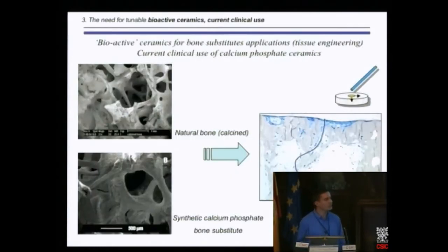So what is the current clinical use? We already use calcium phosphate ceramics. So here is a natural bone, especially the mineral part of this natural bone, and here is a synthetic calcium phosphate bone substitute we have made, for example, in the lab. So the idea is to mimic the structure of the bone at the micro level. This is 1 millimeter in size, 500 microns in size, so about the same type of structure. So the first idea is to mimic the structure. And especially what we want is to have a large porosity. That's completely the inverse of that for the femoral heads, where we need the lowest defects possible. Here we need a large amount of porosity, especially for cell proliferation inside the bone substitute.